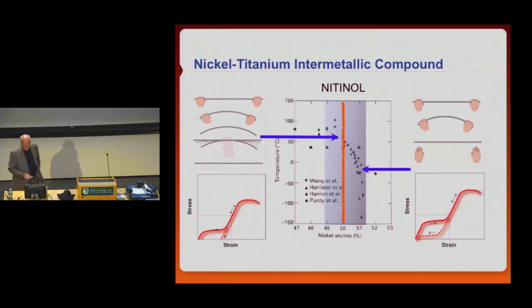Now, if you take an alloy from the other side of this range, and this is the 50.8 atomic percent alloy, the transformation temperature is below room temperature, and if you do a tensile test there, you get the same kind of curve on loading, but when you unload, you can see that the unloading curve comes back too, and that we have a pronounced hysteresis of the stress-strain curve here. And this is very important because the most successful applications of nickel titanium, particularly in the medical world, make use of this particular stress-strain curve.